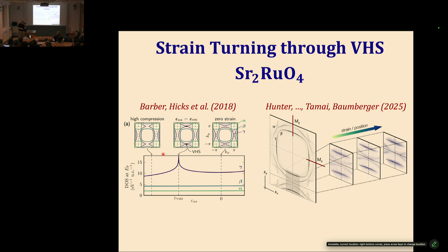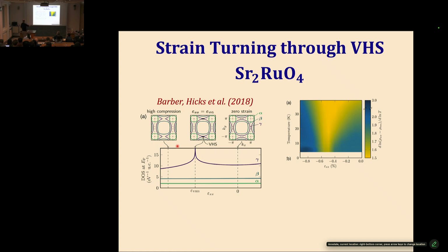And the other really favorable thing about the system is that it's a 3D crystal, but the system is made out of extremely weakly coupled layers. So the system is very quasi two-dimensional. The coupling between these layers is very weak, and that means that this Van Hove singularity really behaves like a two-dimensional Van Hove singularity, meaning that we get this beautiful log divergence of the density of states, which is cut off only at a very low energy associated with the interplane coupling. So all of these conditions are met. What should we see for the resistivity that was shown by Michael?